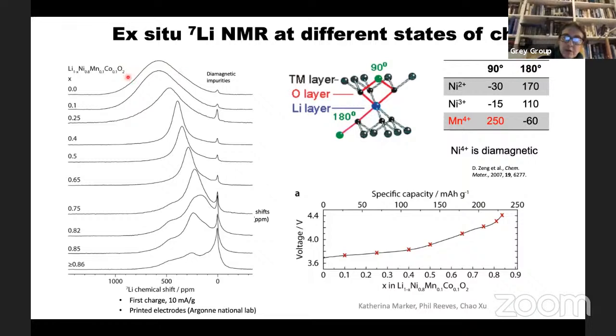And this is what's giving you these broad, very large shifted signals, because you're seeing a whole variety of different local environments. But at the top of charge, I've oxidized. When I pull all the lithium out, nickel 2 plus goes to nickel 4 plus. And for those of you who've got your periodic tables handy, nickel 4 plus is D6. It's low spin D6, so it's diamagnetic.